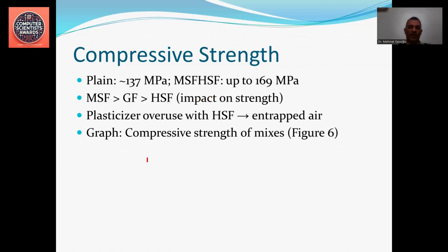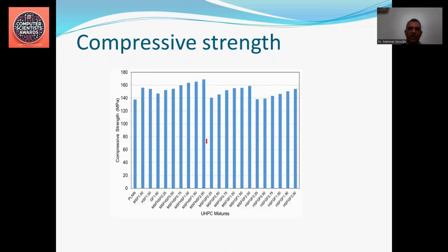The overuse of plasticizers in the case of hook steel fiber mixed concretes and trapped air were observed, which eventually lowered the compressive strength. This graph shows the variation of the compressive strength of the 22 mixes, as you see, plain concrete and 1% steel fibers, 1% micro steel, 1% hook steel, and 1% glass fibers.